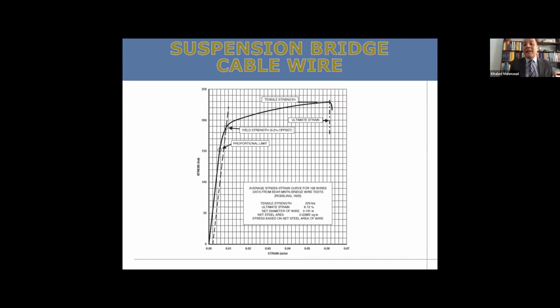1960 megapascal, but that's at the expense of what? At the expense of ductility. So remember, I said that the rod material had about 1300 megapascal, and with the successive cold drawing, you're elongating the grains and imparting that great strength, reaching 1960 megapascal. Actually, it reads more than that.